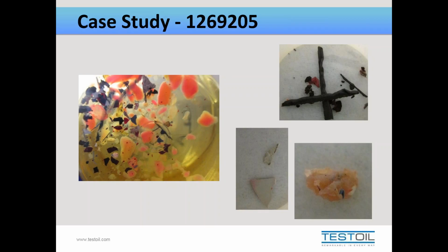So the first one we looked at were the black particles. And we ended up finding out that these were actually silicone rubber. Obviously, some sort of gasket or seal had been damaged and was actually deteriorating and flowing into the system from somewhere. Then we looked at the white particles. And we were able to identify those as an aromatic polyether compound, which is really a material that most likely formed from some type of resin that can often be found in coatings or adhesives.